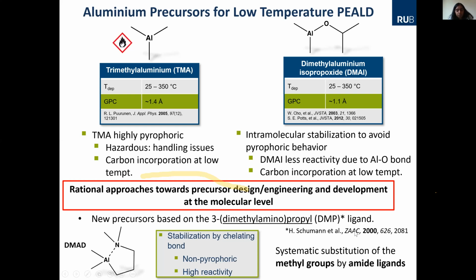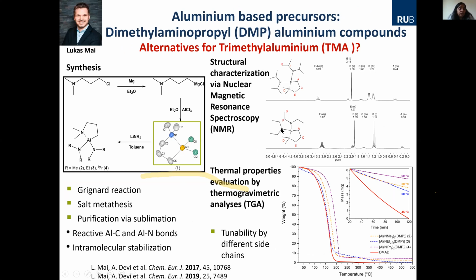So we looked for certain ligands of this type, varied the different groups here, and thought, okay, by using this chelating, basically coordinating this metal center and making it less reactive, we were able to develop a compound, and this was known but not as a CVD or ALD precursor, but just out of interest for inorganic synthetic chemistry. So my student Lukas was the first one to initiate this. So he said, okay, let's try this DMP ligand, whether we can develop some precursors that are not pyrophoric, and can it be a substitute for trimethyl aluminium. This will be a big breakthrough, because then the industry will be very happy, because they can make large quantities.